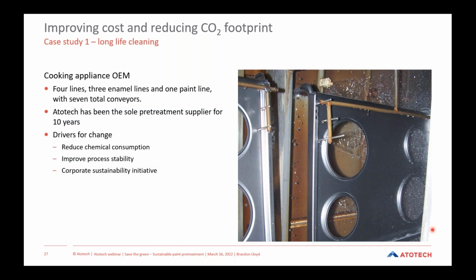This applicator has 4 production lines, 3 of them being enamel lines and 1 paint line with 7 total conveyors. In this example here, we'll focus pretty much exclusively on the paint line. Atotech in this scenario has been the pretreatment supplier to this applicator for about 10 years. And their key drivers for change at that time were reduced chemical consumption, improving the process stability, and their corporate sustainability initiatives as well.